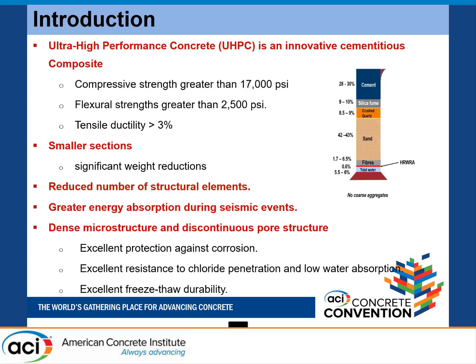But it's a very high density concrete, very less porous. The permeable porosity we measured in the lab is way less than 2%. Even then, those pores are not interconnected. So ingress of harmful ions like chlorides and sulfates is nil. Freeze-thaw durability is excellent. This is the material for the future.